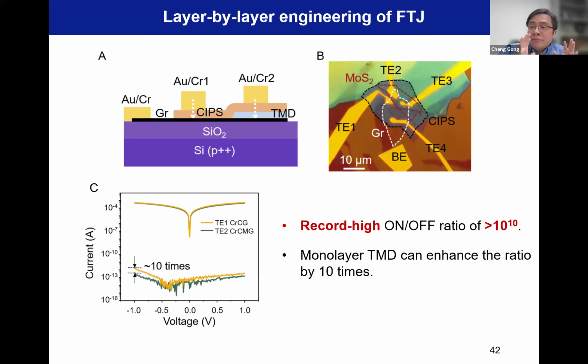I think there are three major enabling physics that cause this record high on-off ratio. First, the CIPS has a very minor, trivial amount of defects compared with the oxide thin layers, which have a lot of defect vacancies. So the band gap of CIPS is clean. So you don't have a lot of defect states in the band gap to cause indirect tunneling. So this is one thing.